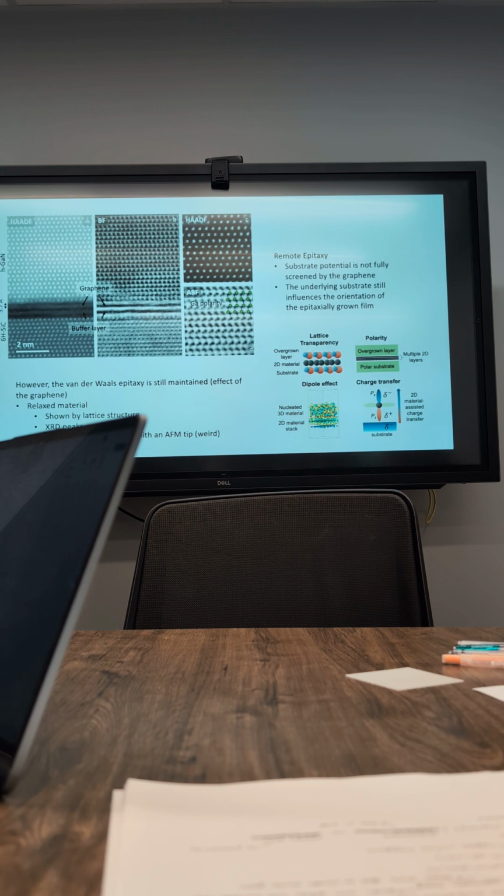Okay, XRD. Yeah, they did glancing angle XRD, grazing incidence, which should just be finer. XPS isn't gonna work here, because it's surface sensitive. You only get the top gallium nitride layer. You wouldn't be able to see the graphene, it'd blast right through it.